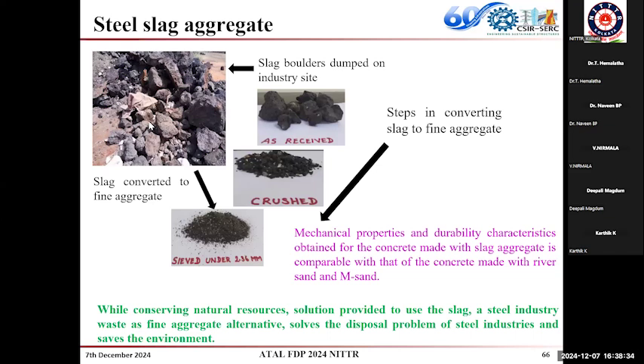So these are the slag boulders, and they have been crushed and sieved through a 2.36 mm sieve. This fine aggregate is called slag fine aggregate after crushing. And this slag fine aggregate is used instead of conventional river sand.